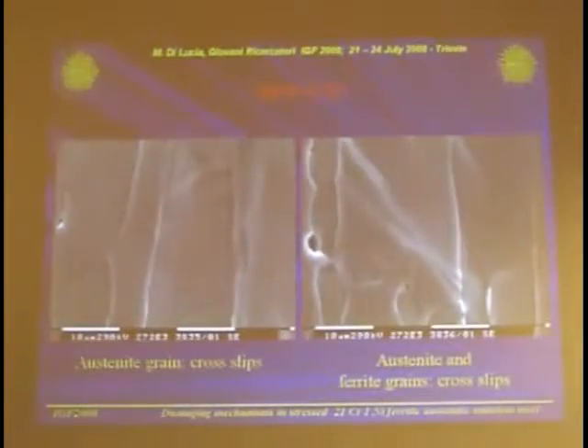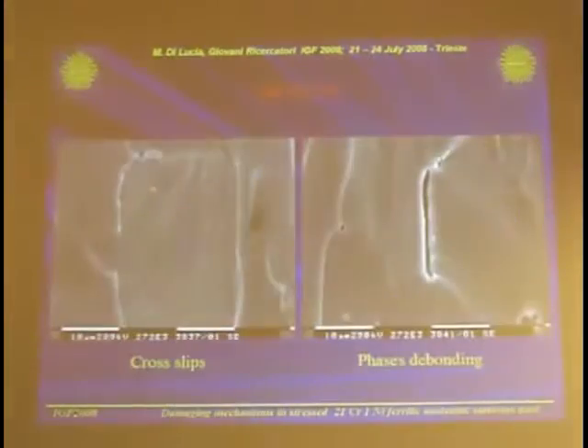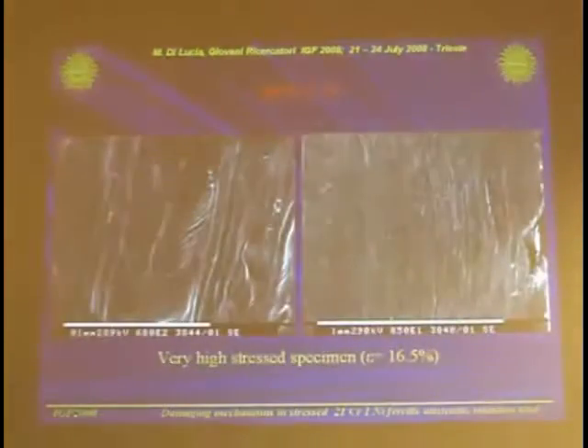Other images obtained during microtensile tests at different magnifications are reported. It is possible to observe cross slips in austenitic and ferritic grains, and it is possible to observe a phase debonding mechanism. Then the following figure shows a very high stress concentration.